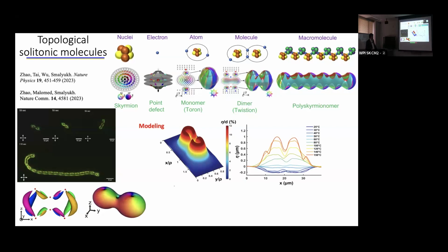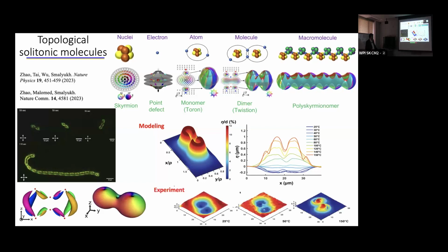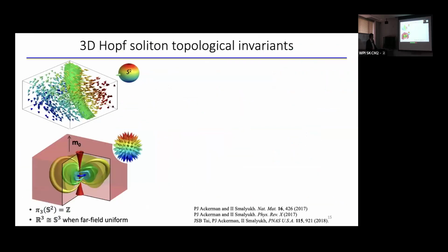And you can see again, we can go from these valleys that have a level lower than the flat surface around to the mountains, right? But the very interesting features that you can see in here emerge from combining multiple topological solitons into solitonic molecular analogs. And again, in here you can see these experimental results that illustrate such actuation.